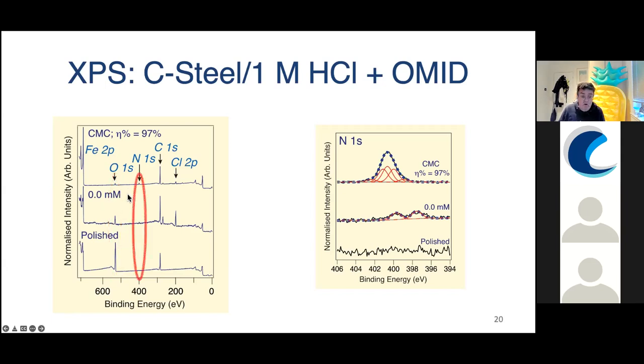As well as that, we also see the appearance of a nitrogen signal, which becomes more intense once we have the inhibitor at CMC, which remember contains three different nitrogen atoms. So let's look at the right-hand side. The right-hand side is showing this nitrogen 1s core level in more detail, the signal from the nitrogen atoms at the surface. You can see the polished surface is flat. We don't see any nitrogen. We see two small bumps, two small peaks, without any inhibitor there. And that's because of enrichment of elements within the sample as it corrodes. So nitrogen is just enriched slightly at the surface. That's why we see something.